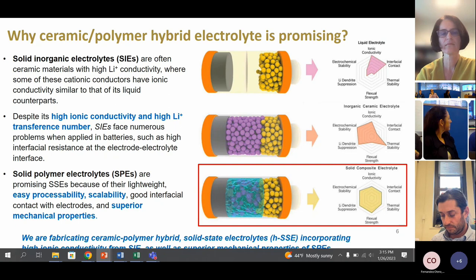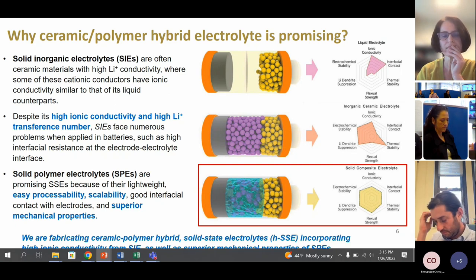Now, the problem with the liquid electrolytes is that dendrite suppression, thermal stability, and electrochemical stability are very poor. Whereas for the ceramic, there is high electrochemical stability and dendrite suppression. A dendrite is essentially an internal short. They produce these small microcracks, and it allows charge transfer between electrodes and shorts the material.